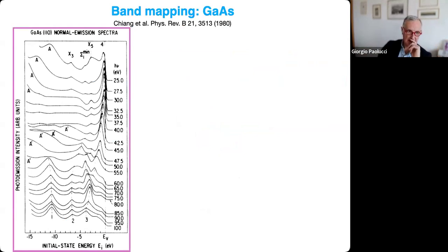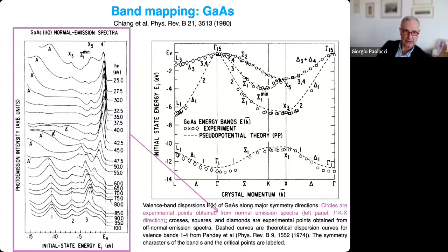This figure is taken from a very old paper, but as you can see, it was published in 1980. So it was even before I got my master's degree, so to tell you how old this paper is. But nevertheless, it shows you the basic feature here, these are measured at normal emission. You change the photon energy in a range from 25 to 100 electron volts, and you see that the position of peaks changes, and you can compare that to the calculated band structure. And you see that the positions agree. I mean, you can very effectively verify what the calculations have shown.